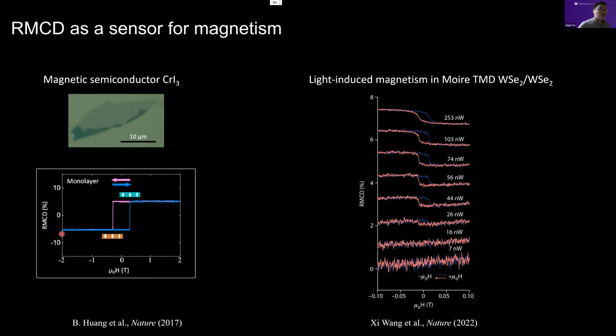What you can see is that if you sweep a magnetic field, the RMCD signal shows a hysteresis loop. The hysteresis loop marks the development of long range order, the ferromagnetism. And another quite interesting feature is that at zero magnetic field, a remnant RMCD also marks the possible development of ferromagnetism. Another interesting phenomenon we observed recently is that you can use light to dope the Moiré superlattices a little bit, and you can see this light-induced ferromagnetism inside the system as you change the power of your laser excitation.